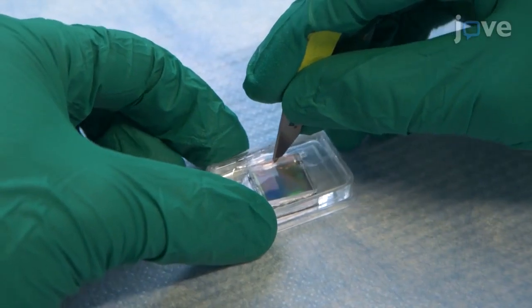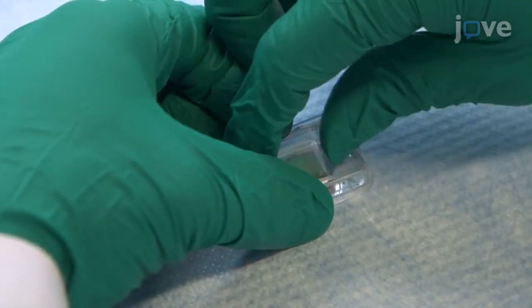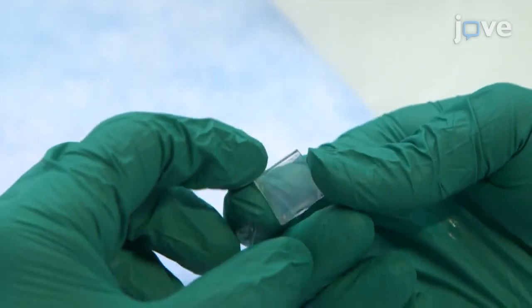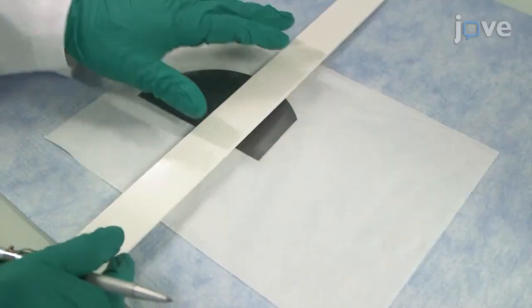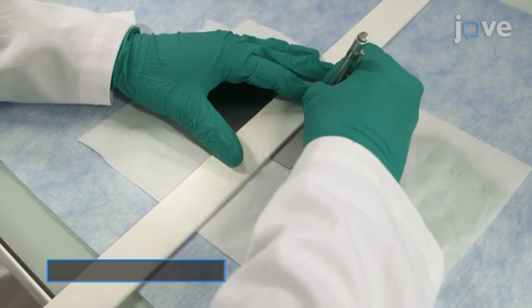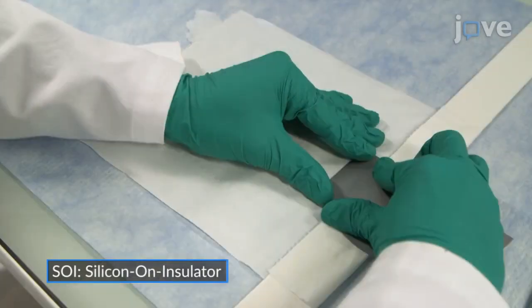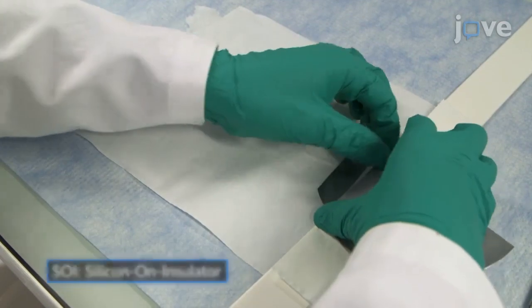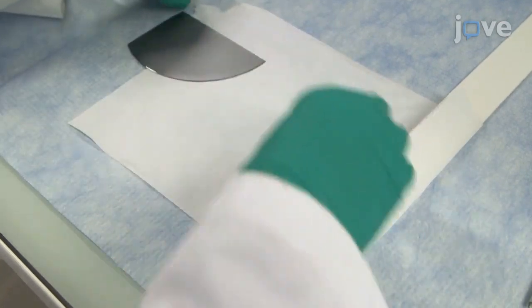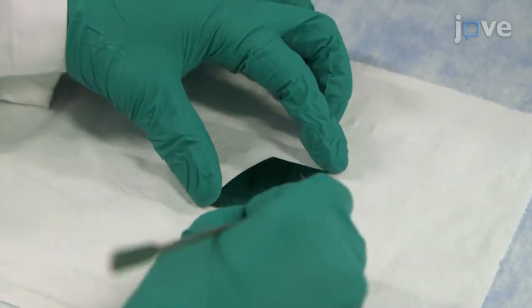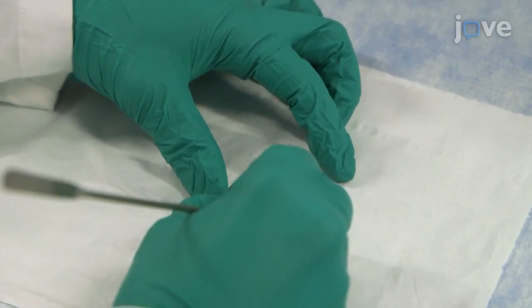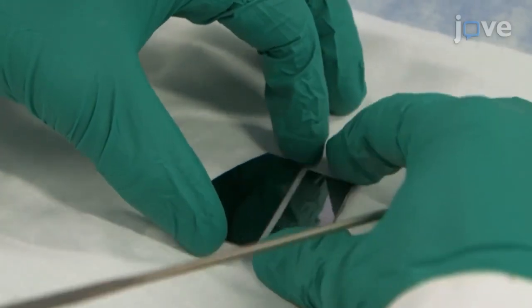Replicate the silicon master using the PDMS solution as described in the manuscript. Prepare 2 by 6 cm sized substrates by cutting a 2-inch P-type SOI wafer in a direction parallel or perpendicular to the wafer flat using a diamond tip, ensuring that the conductivity of the silicon device layer is between 1 and 10 ohms per centimeter.